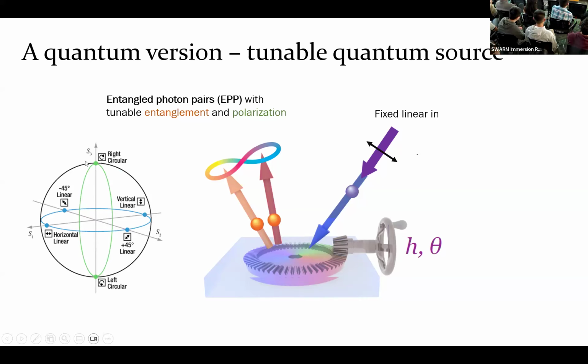So if you overlay this onto the previous Poincare sphere that I showed, now you can show a similar sphere where the top of the sphere is a quantum state with no entanglement, whereas the states on the equator are quantum superpositions of vertical-horizontal plus horizontal-vertical. These are the possible polarizations of the 2 photons that come out of the system, and when they're entangled, you cannot tell exactly what polarization they have, but they are correlated in a quantum way.